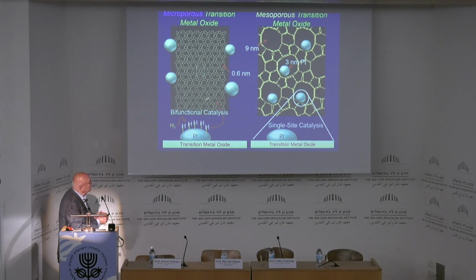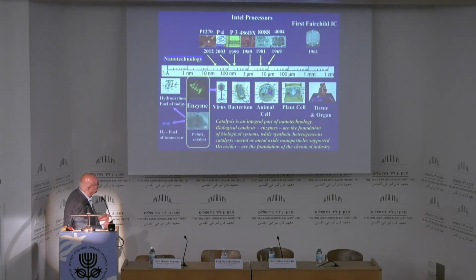Now, if the mesopore is large, what you find is that the smaller nanoparticle, like the 3 nanometer platinum, can go inside the pore, and this is called a single-site catalyst because the chemistry occurs at the oxide-metal interface. Now, let's go to the next technology.